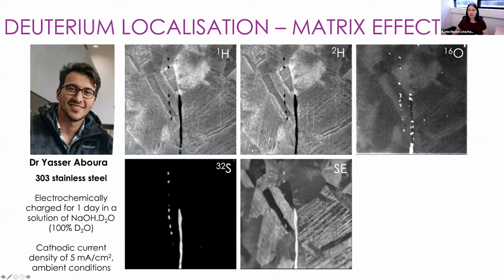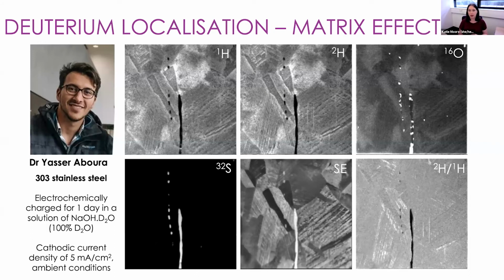Well, in fact, it doesn't. This is the matrix effect. This is what we see when we have different crystallographic orientations being imaged in the NanoSIMS. Some particular grain orientations will emit more secondary ions than others. So we obviously need to be able to account for that when we're looking at our images, because that complicates our interpretation. And what we do is we simply take a ratio image.